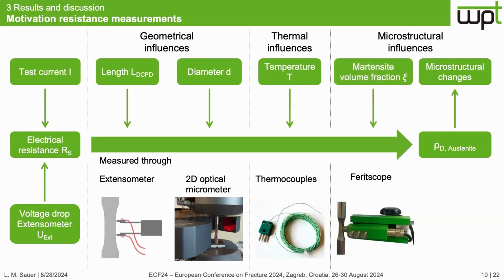And for the influence of martensite transformation, the martensite volume fraction was measured with a Feritscope, so that as a result, the temperature-independent electrical resistivity of the austenite was determined, which no longer depends on the geometry, temperature, and martensite, so that the microstructure changes can be evaluated, for example, the dislocation density, voids, or grain size.